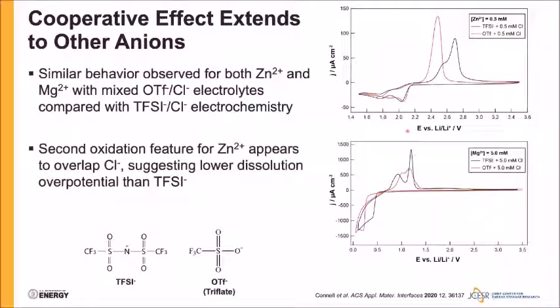But very interesting for the zinc triflate system, while we again see 2 distinct reduction events, we only see 1 obvious oxidation feature. And so what this seems to suggest is that the combination of triflate and chloride shifts this second dissolution event to a potential very similar to that of chloride. And so the question here is, can triflate be used to mimic chloride? Can we start to move away from chloride in these electrolytes to improve the versatility of these systems?